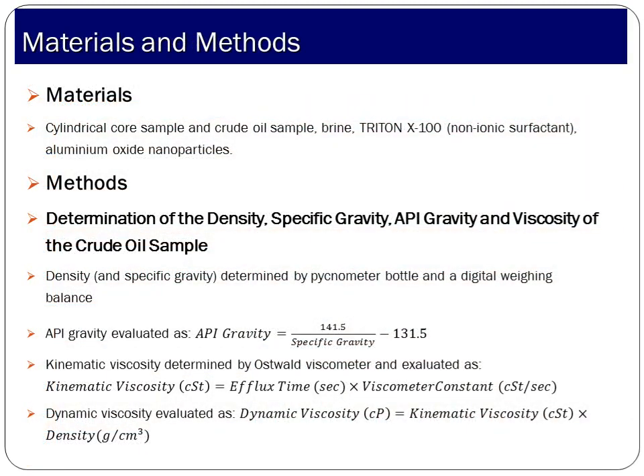Now, materials and methods. Materials used are cylindrical core samples, crude oil sample, brine, Triton X-100 surfactant, and aluminum oxide nanoparticles. Methods comprise determination of density, specific gravity, API gravity and viscosity of the crude oil. API gravity is evaluated as 141.5 over specific gravity minus 131.5. Kinematic viscosity is determined by Ostwald viscometer and evaluated as efflux time times viscometer constant, while the dynamic viscosity is evaluated as kinematic viscosity times density.